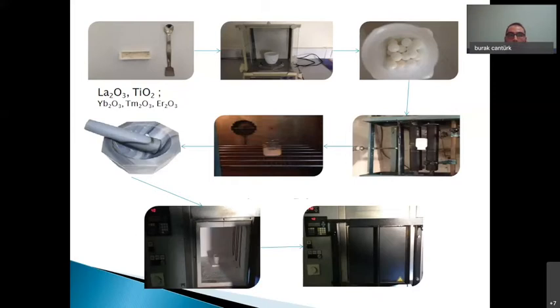We carried out the preparation stage as follows. We used lanthanum and titanium oxide as the starting materials. Rare earth ions such as ytterbium, erbium, and thulium were doped with the appropriate stoichiometry in the site of lanthanum. We have succeeded in producing them with conventional basic solid state methods.